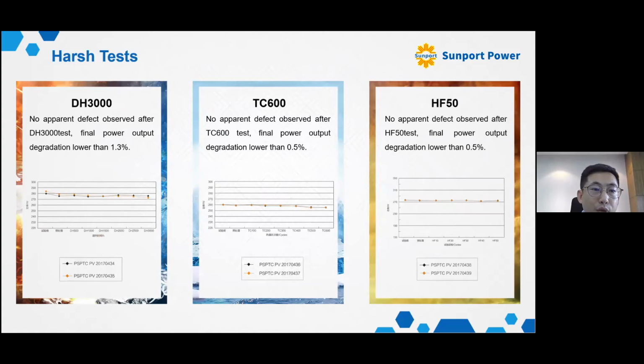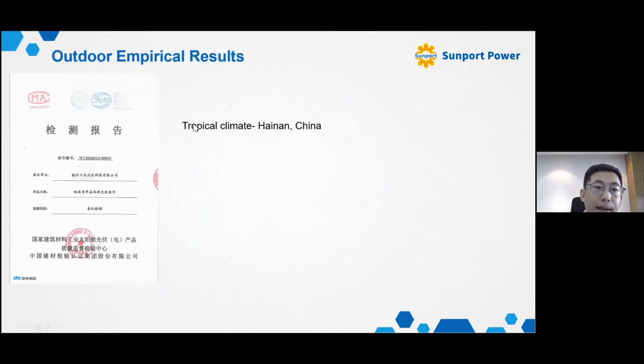To prove the durability of the MWT structure, we carried out triple tests based on IEC standards such as DH3000, TC600, and HF50. Results show that the power degradation is very tiny, which is much lower than the IEC standard. In addition, we have sent our samples to different authorized third parties or institutes, including TUV Nord and other institutes.